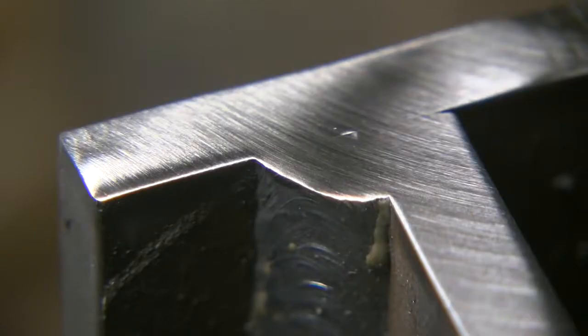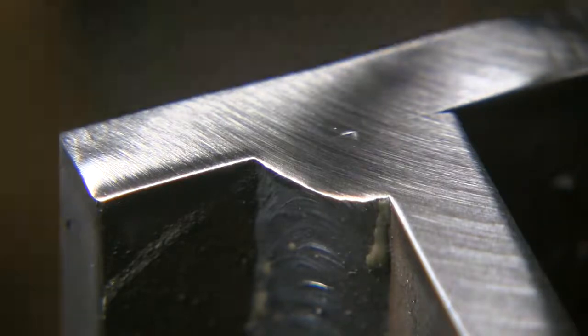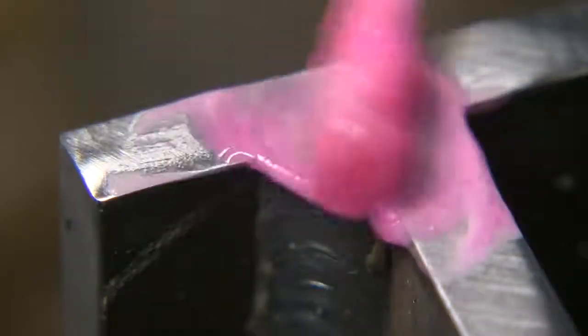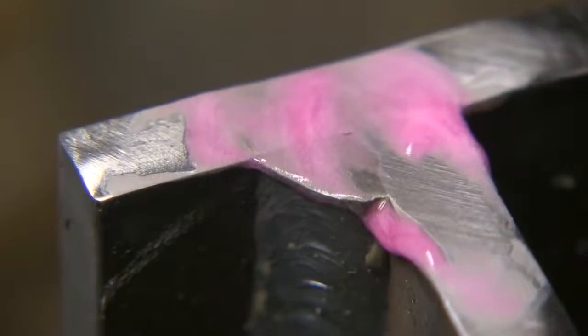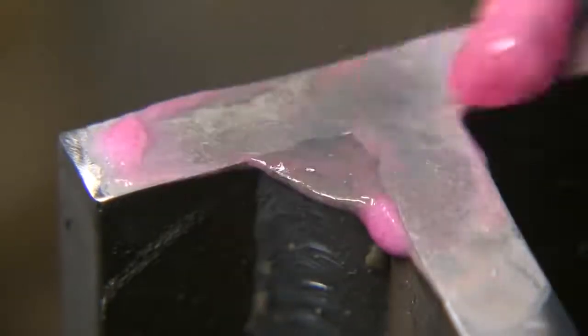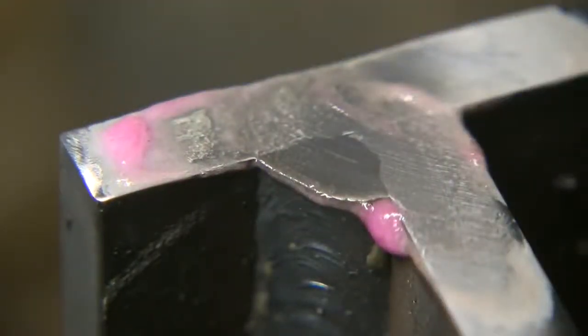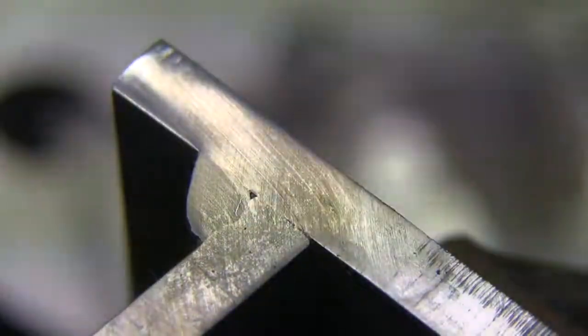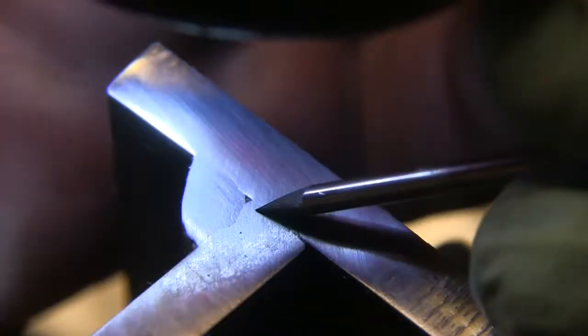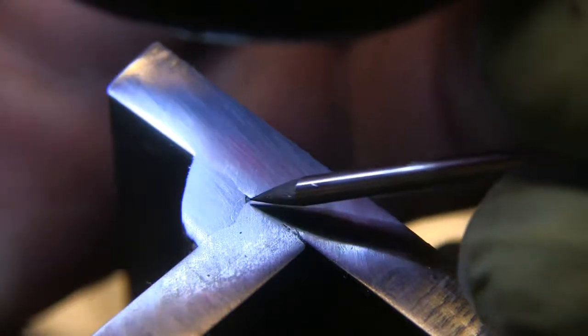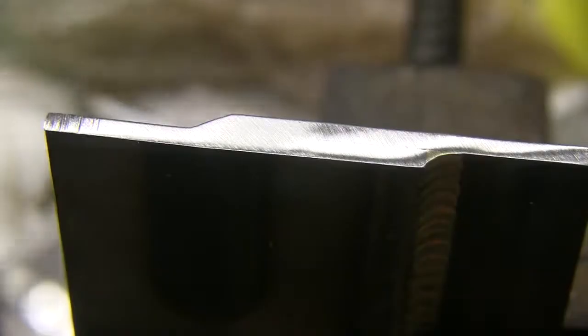All right, now let's look at the downhill. We see problems there already before we even get an etch on it. There's lack of fusion right in the root of the joint. It didn't make it into the root of the joint. And as we etch further and further, we see that it almost looks like a braze joint. Really no depth of penetration at all, barely bonded in some areas. It got a little bit past the surface here and there. It looks like a braze joint, honestly.